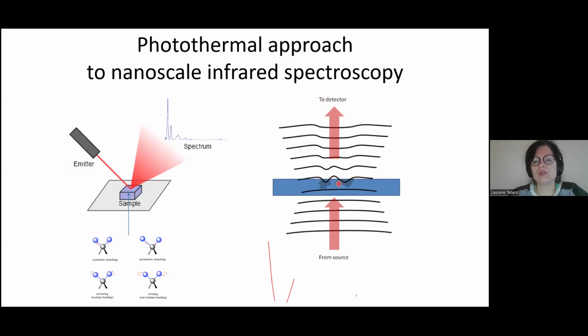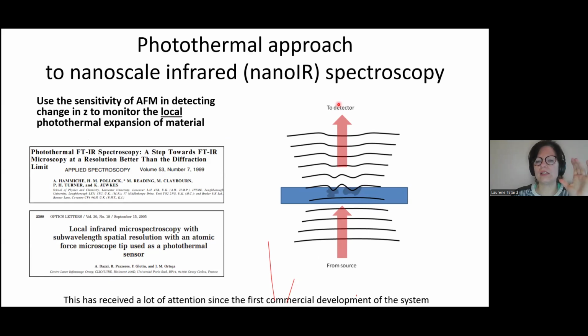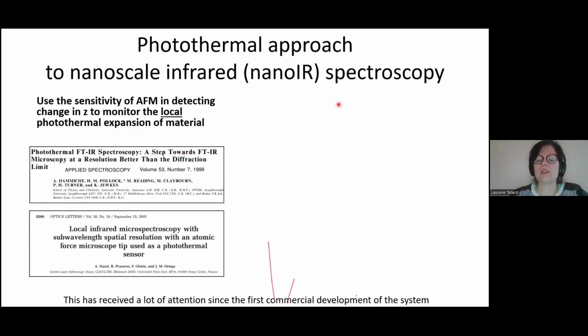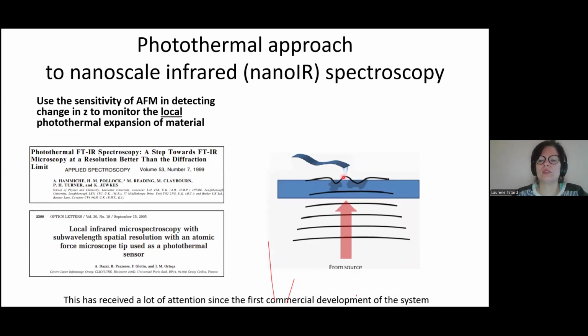And why is that? It is because the infrared light excites vibrational modes in molecules. So you have the symmetric vibration of the chemical bond, you have the asymmetric, and all these different vibration modes happen at different wavelengths. So as these vibrations are excited in the system, then the light is used up, or the energy is used up for the vibration and it doesn't make it to the detector. So that's the common way of doing infrared spectroscopy at the large scale. And so then some researchers had the idea that if the material absorbs like that, that means it's going to locally heat because the vibration of the chemical mode is going to make the material expand. And because the AFM tip is so sensitive, maybe we'll be able to detect this small vibration or expansion, photothermal expansion of the material.